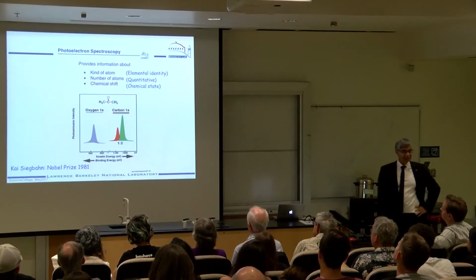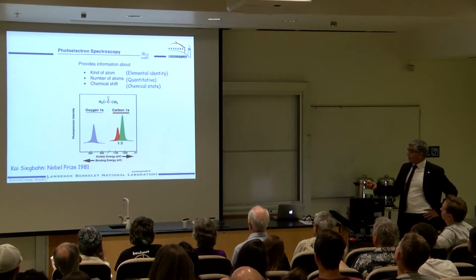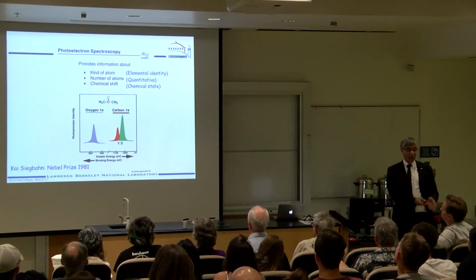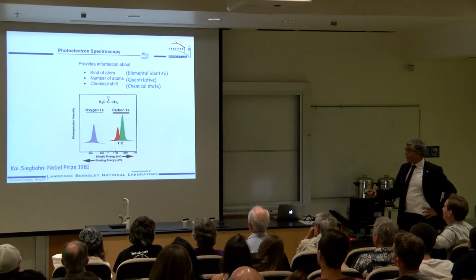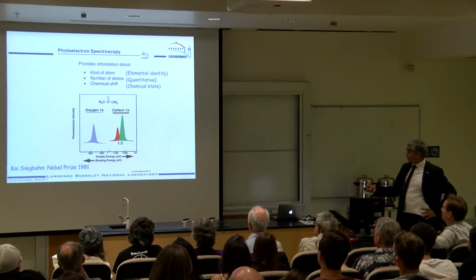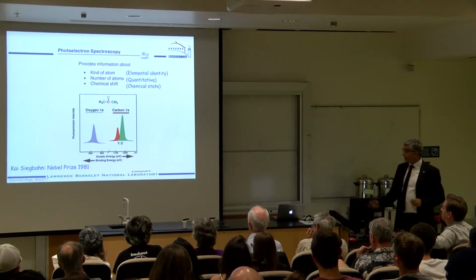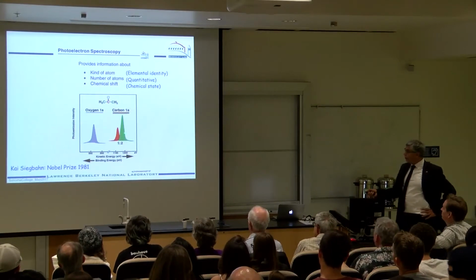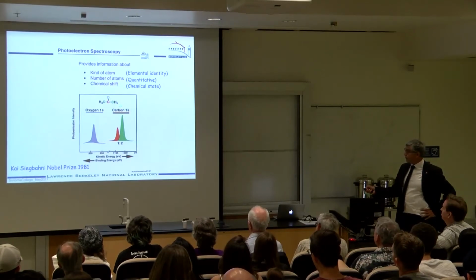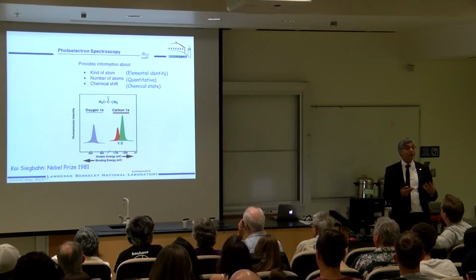Look at acetone. We do not know acetone is there. It has carbon atoms, two kinds. One is the red carbon, the other is the green carbon. We don't know in the material that it is actually red or green. Then there is an oxygen. If you take a spectrum and look at the carbon, you see two peaks instead of one, and they are not at the same energy position, they are shifted. So it means this carbon has a different chemical bonding compared to this carbon. This is hydrogen and this is more electronegative. So doing this class of experiment, I can understand the chemical bonding.